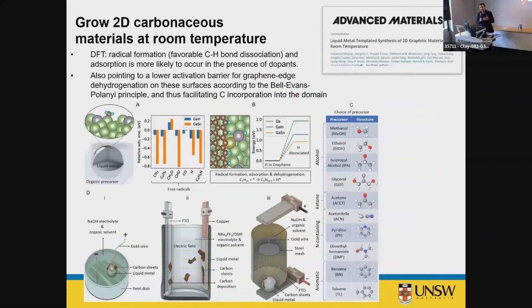Even we could extend this to graphitic material. So we did DFT calculation. We saw that if we bring some organic precursors to the surface, and we apply a voltage in an electrochemical setup, then we can break them on the surface, dehydrogenate them. So methanol, ethanol, propanol, and the rest as you see. Acetonitrile, pyridine. Some of them have nitrogen, some of them without nitrogen.